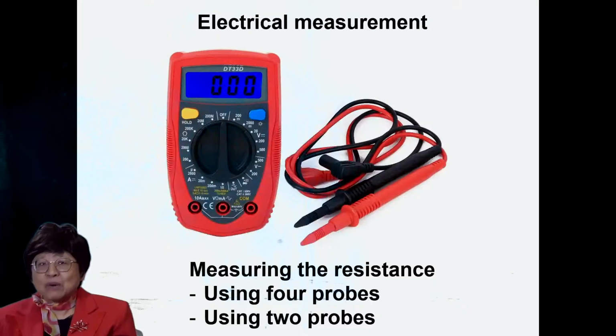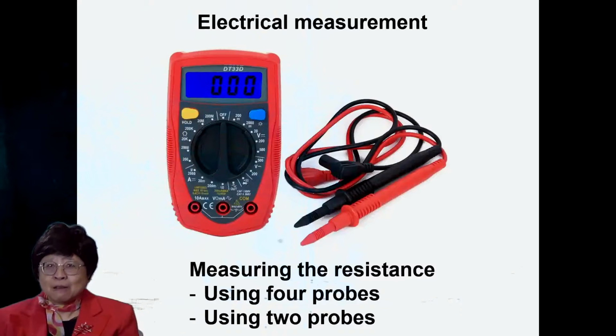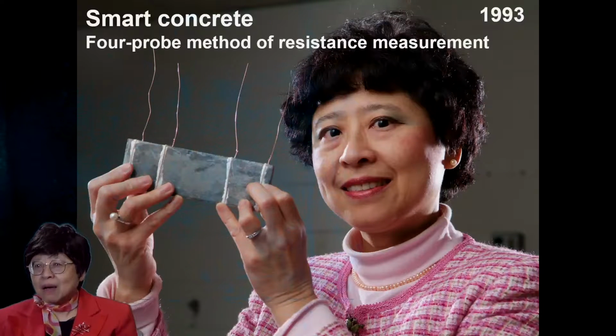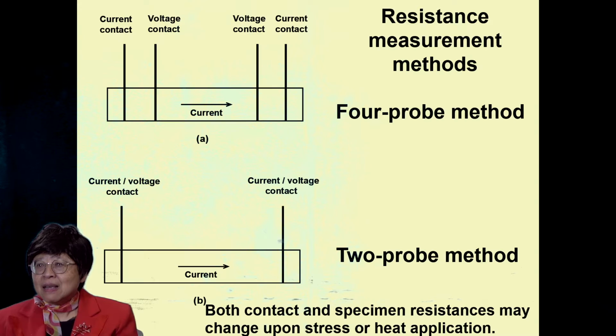Electrical measurement sounds easy using a meter, but there are many pitfalls. For measuring the resistance, there are two methods, the 4-probe method and the 2-probe method. Here I'm holding onto a sample with 4 wires wound around, and this is the 4-probe method. In the 4-probe method, the outer 2 probes are for sending in the current. The inner 2 probes are for measuring the voltage. As a result, there's no current going through the voltage probe, and the measured resistance excludes the contact resistance. However, if one uses the 2-probe method, the measured resistance includes the contact resistance.